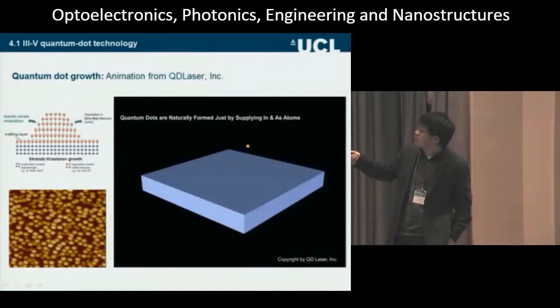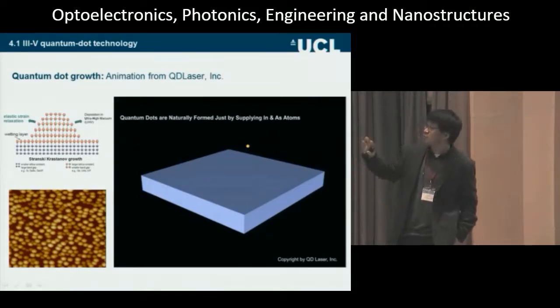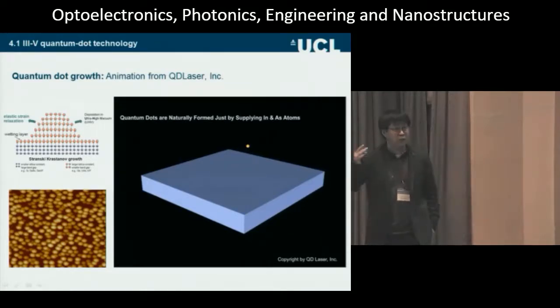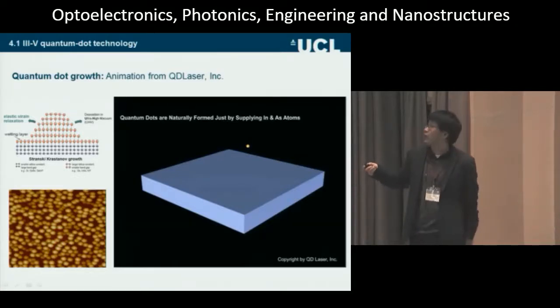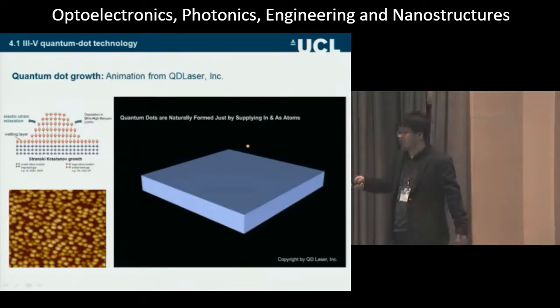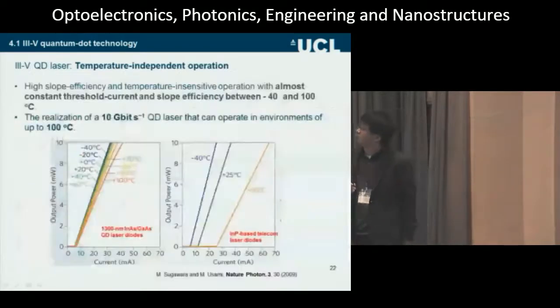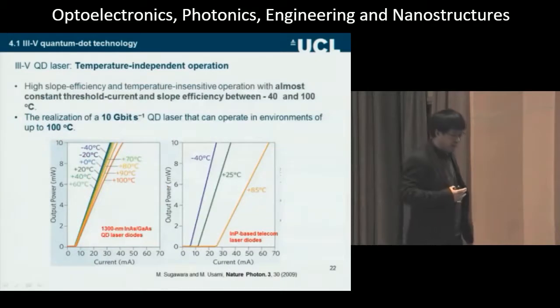You can see indium arsenide has a big lattice constant, so you get strain relaxation and it forms 3D quantum dots. These quantum dots are normally a few nanometers high and 20 to 40 nanometers wide. If you do AFM, you see the surface looks like a lot of jelly beans. I have an animation here, but I can't show it today, which basically tells you how to grow quantum dots on the surface.